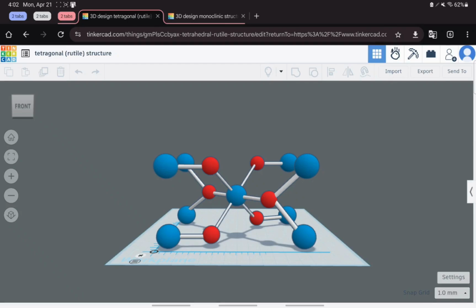Because of this, all the vanadium atoms have equal sharing of d orbital electrons, which results in the metallic behavior that we see. However, in the monoclinic structure, which is below the transition temperature, dimerization causes vanadium atom chains with alternating short and long vanadium-vanadium bonds. This pattern localizes d orbital electrons within the dimer, which results in the insulating behavior.